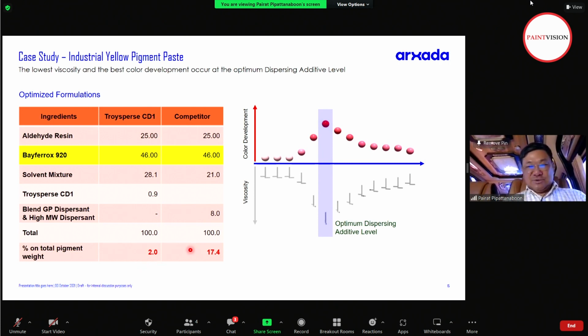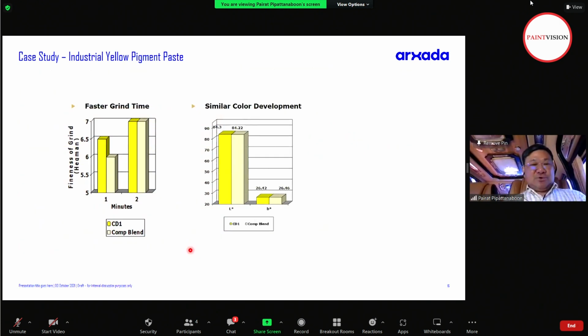All right. So let's see, after the pigment dispersion demand, how do you derive this performance? You can get faster grind time than the competition, and also similar color development. But remember, you use CD1 only at 2% on Bayferrox yellow pigment. With the current incumbent dispersion, you have to use two dispersions, and the dosage is around 17% on pigment weight.